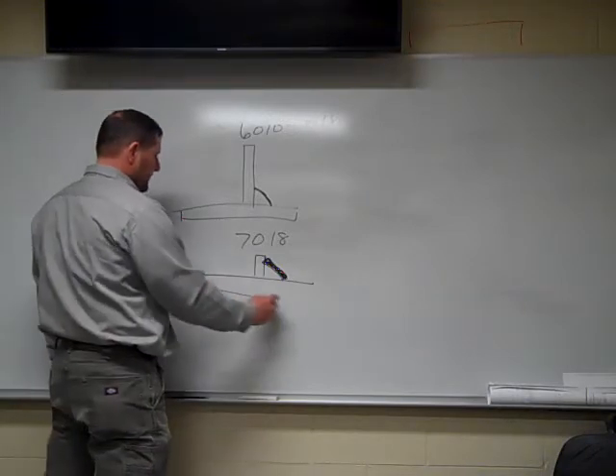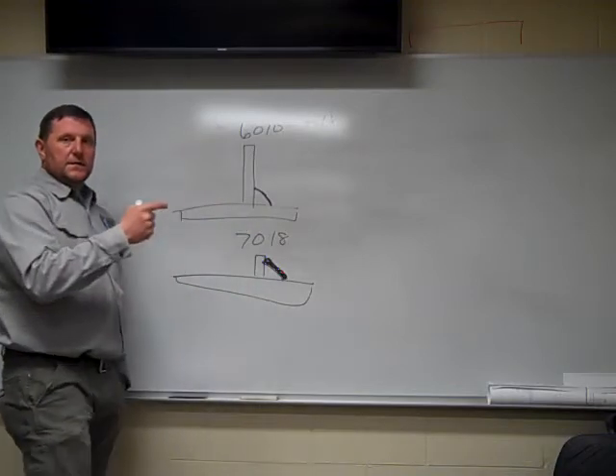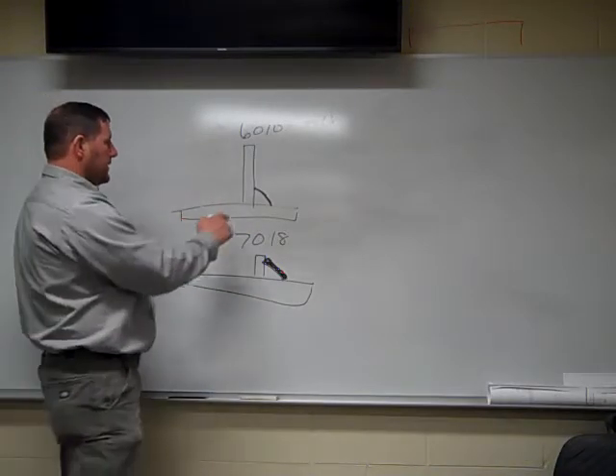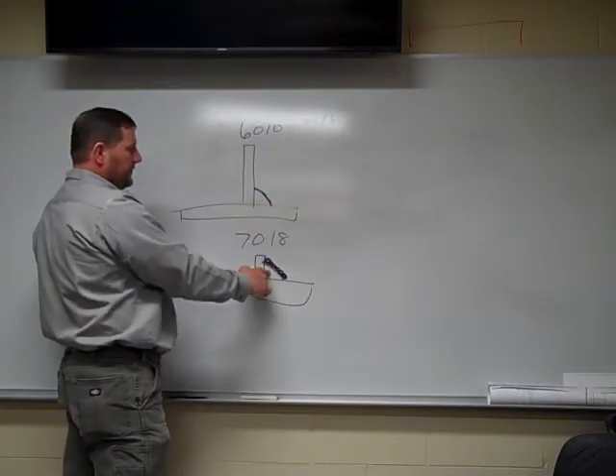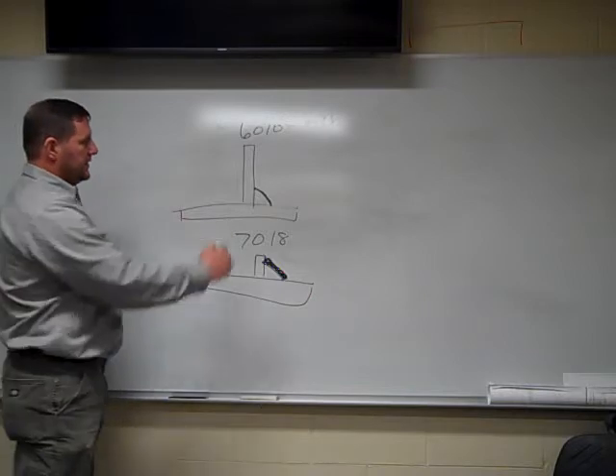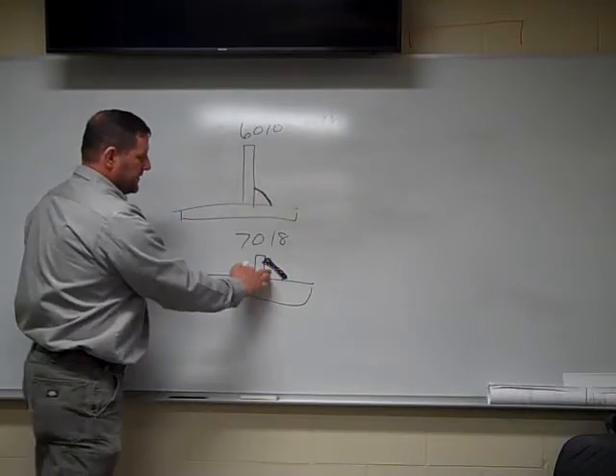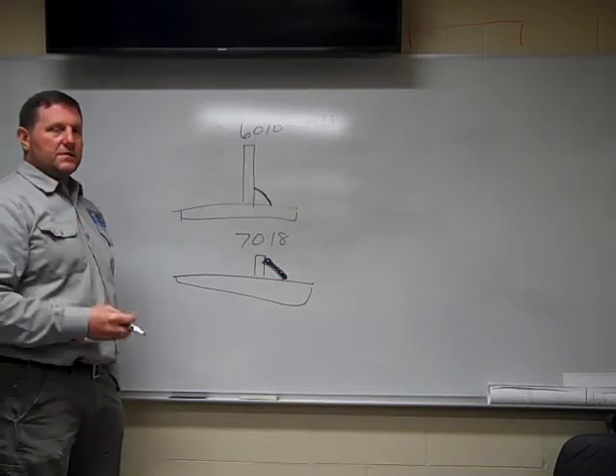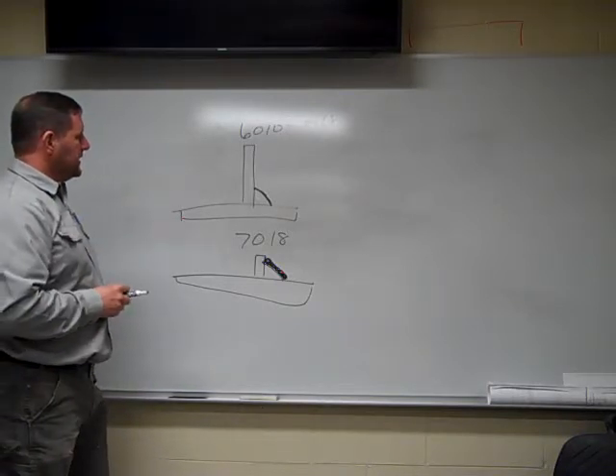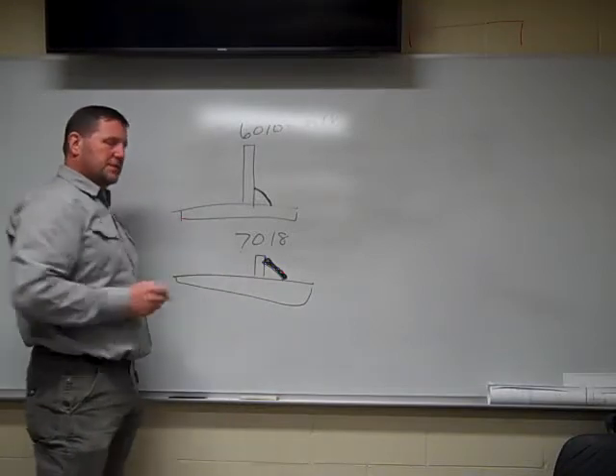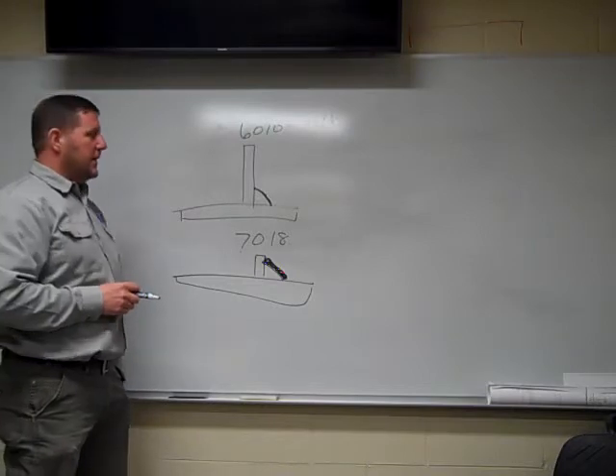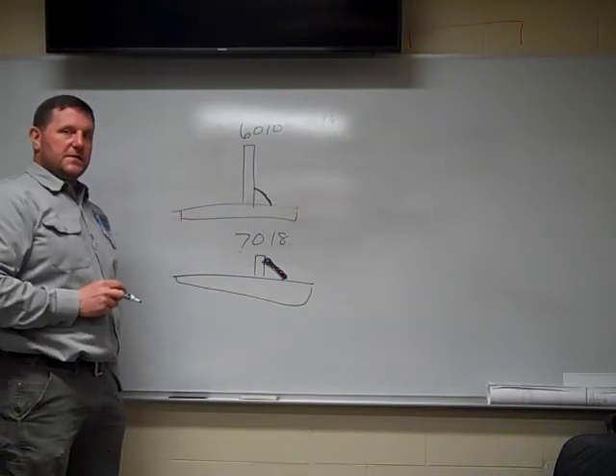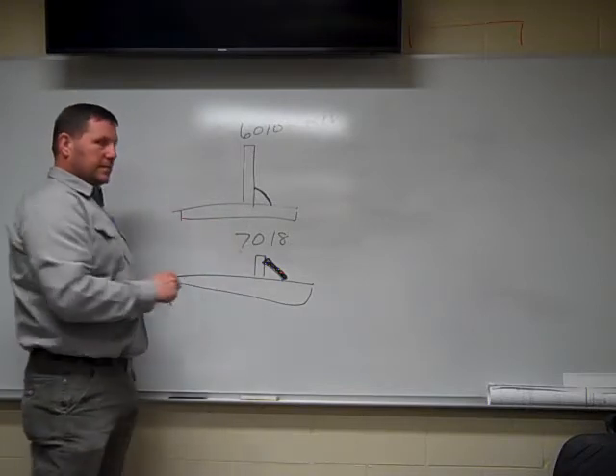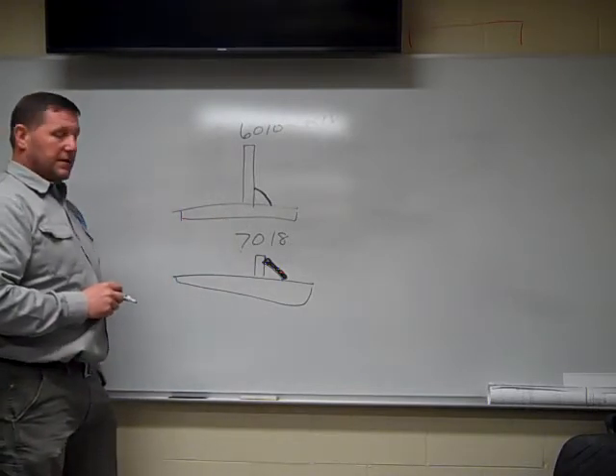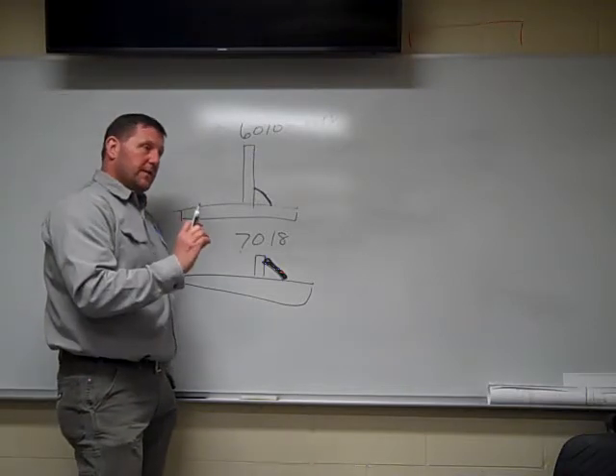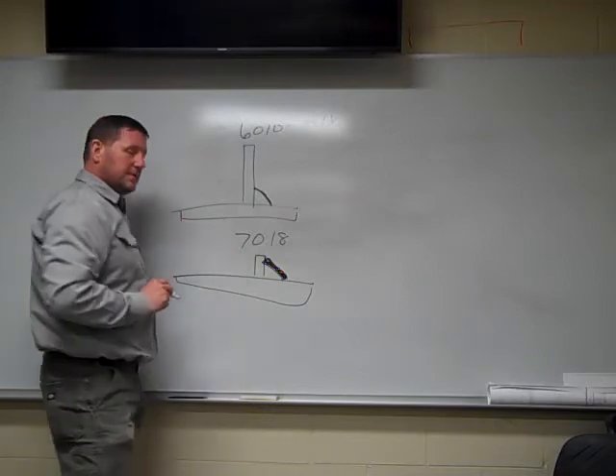Now when you think about slag covering a weld, it's like a blanket that covers that weld. We have a very thin blanket with our 6010, a very heavy blanket for 7018. So you can see that this one here is going to cool a lot faster than a 7018. 7018 is going to cool a little slower because we've got more slag covering than a 6010. But you have better electrical characteristics, a smoother weld with the 7018. Not near the amount of fusion that we're going to have with the 6010. You're going to get a lot more fusion with your 6010 compared to your 7018.